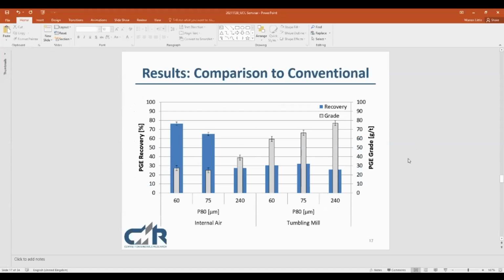Also compared flotation performance versus conventional milling. So this is just a tumbling mill, laboratory scale tumbling mill. And for all the grinds achieving significantly higher recoveries, despite the poor froth stability, for the internal air classifier vertical roller mill setup and the tumbling mill products. So maybe at the coarse grind we're a bit more comparable there, but at the finer grinds, the 60 and 75 micron, we're seeing a large difference in recovery.